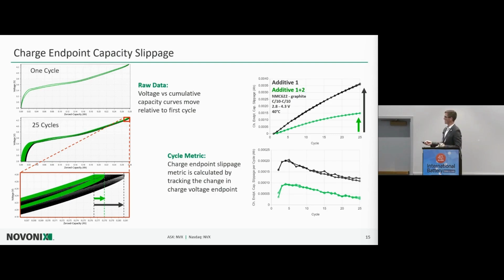So there are a pair of cells here, different types of additives. Additive 1 is just vinylene carbonate in this cell. Additive 2 is vinylene carbonate and propane sultone. And that propane sultone additive really lowers the rate of these slippage-based mechanisms happening at the cathode. And we can see that in a couple cycles.